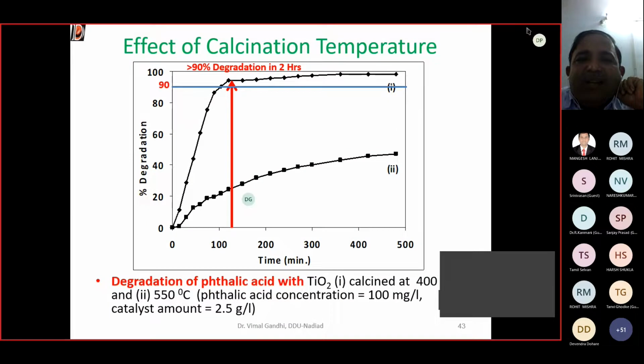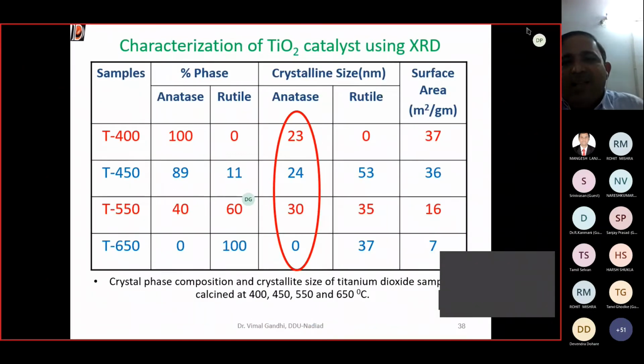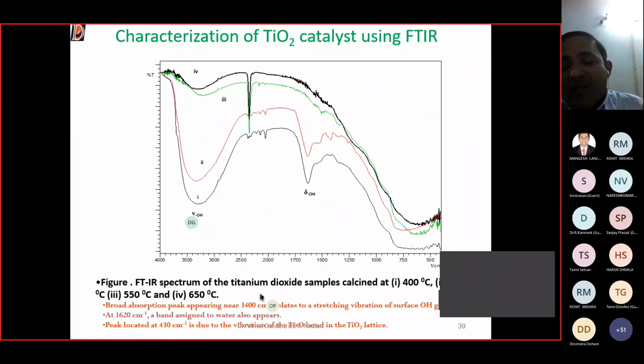So, and the other sample is not giving you a good result. And now I think there is no need to give you the reason why. Because the sample calcined at 550 degrees centigrade has less surface area, and the rutile phase is observed. If you remember this slide, you have half of the surface area, that is 16 meter square per gram, for the sample calcined at 550 as compared to the sample calcined at 400. As well, in 400 you have 100% anatase phase, here you have only 40%, which is the more catalytically active phase.